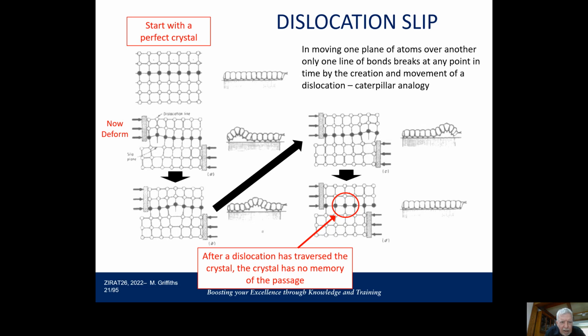This part is realized straight away, but this part of the crystal doesn't really know what's going on back here. Maybe a little bit. There's a little bit of strain energy, elastic displacement coming on here, and you can see that there. But as the dislocation moves across, eventually that elastic strain which exists here is converted into a plastic strain. So we go by this mechanism, and that way we move from one point to the rest.